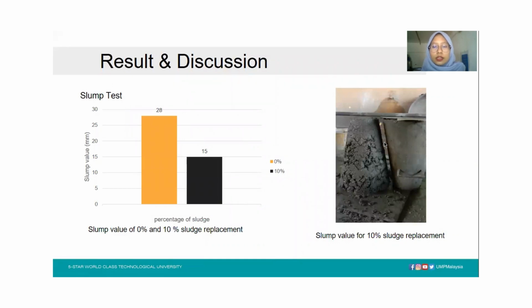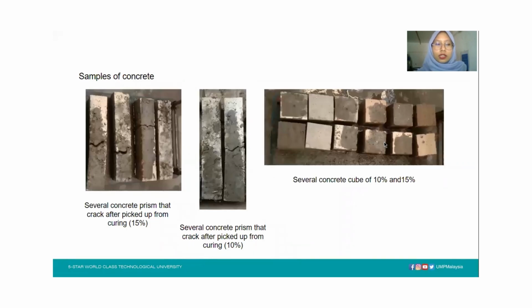The result obtained for slump test is for 0% and 10% sludge replacement. The picture shows the slump value for 10% sludge replacement. This is the several concrete samples, where some are unacceptable and some can be tested.